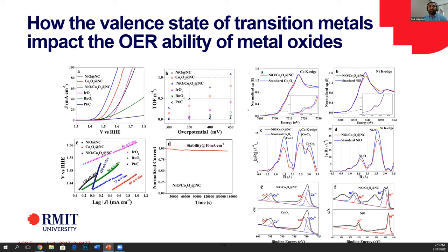If you look at our EXAFS study, you will find that when the nickel and cobalt oxide come close to each other, there is a shift in the peaks. And we found the same thing in our XPS results, which confirm that we have a higher oxidation of cobalt: we have more Co3+ than Co2+.